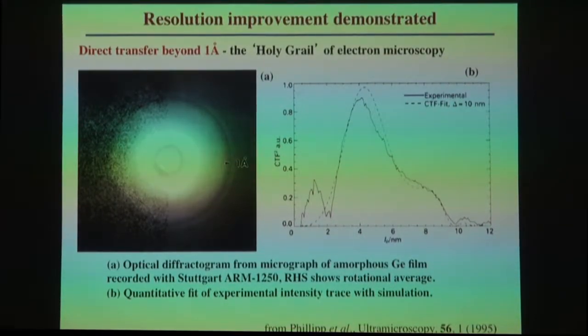This is from the work of Fritz Philipp, published in 1995, on the Stuttgart ARM 1250. This is demonstrating direct transfer beyond 1 angstrom. For many, many generations of microscopists, this was the so-called holy grail. We would aspire to reach it, but we would never quite achieve 1 angstrom resolution. Well, in this particular case, there is what is called a diffractogram. The sample was amorphous germanium, and if you get the optical diffractogram, rotate it, and do some measurements, you'll see that the first zero of the transfer function is sitting right there at 1 angstrom. There is even a bit more information beyond the 1 angstrom level. And so higher voltage microscopy achieved better than 1 angstrom.